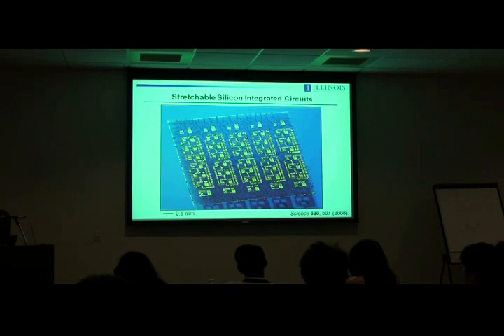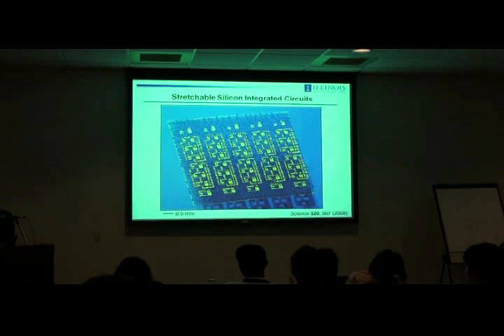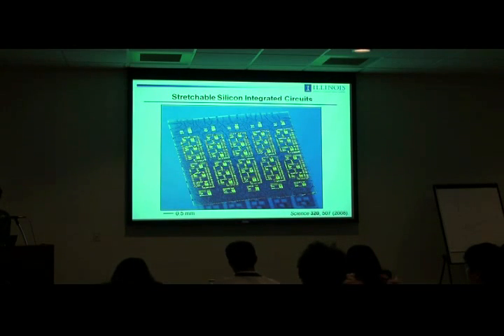The other part of the answer is that monocrystalline silicon, in that sense, is good not only because it has attractive electronic properties, but it's also known to have very good fatigue resistance because there are no grain boundaries to migrate during cyclical stress loading. And that's already established from the MEMS community. We do our own fatigue testing, but I think there's ample reason to think that monocrystalline silicon is good not only for electronic properties, but also fatigue.